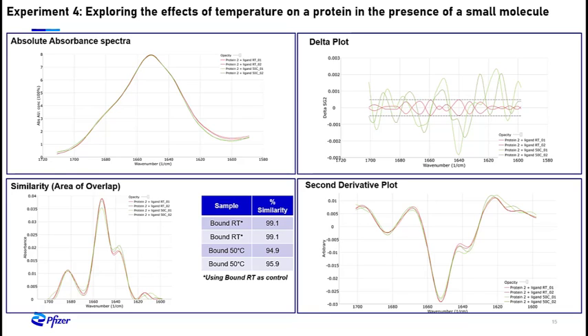In this next slide from experiment 4, you can see from the first set of data in the absorbance spectra in the upper left-hand corner that the data is well overlaid. At the right is the delta plot with the heat-treated protein ligand complex in green, showing change within that sample set. Below that is our second derivative plot, where you can clearly see something's going on in the 1638 region here upon heat treatment, again in green. Our similarity plot to the left clearly shows that with heat treatment, there is some loss of alpha helicity and a gain in beta sheet content. Although not overall dramatic changes, but remember, we have a stabilizing ligand bound to the protein here.